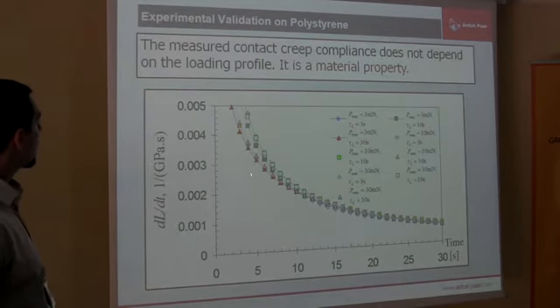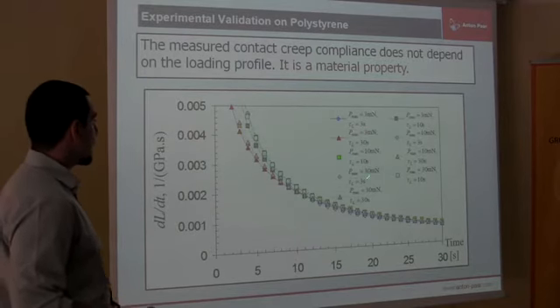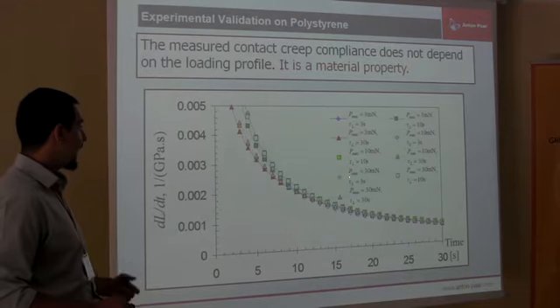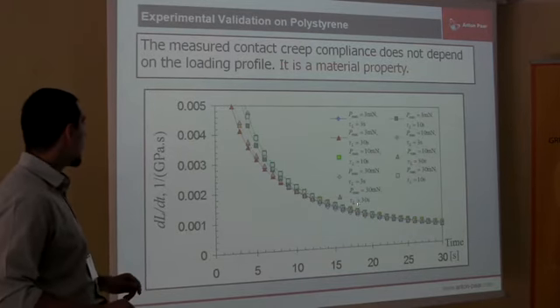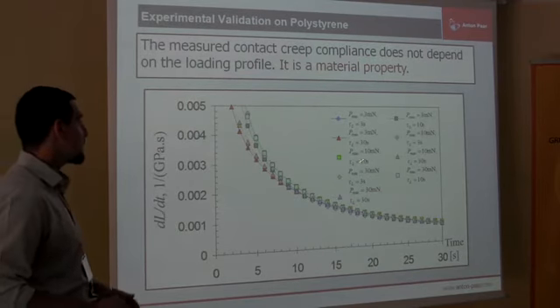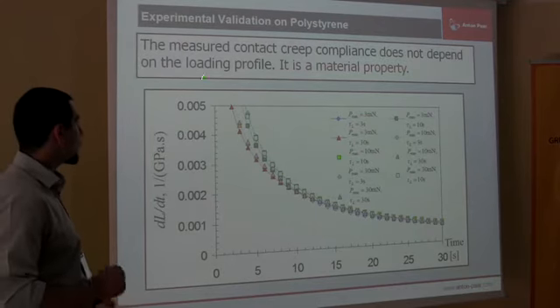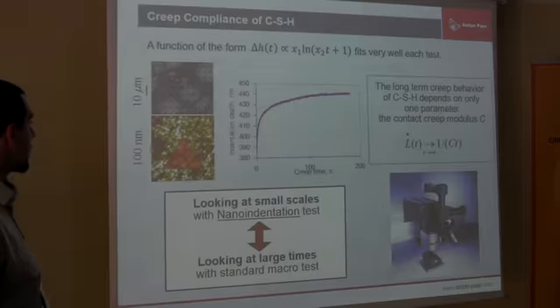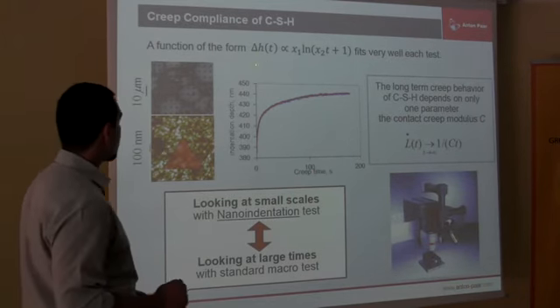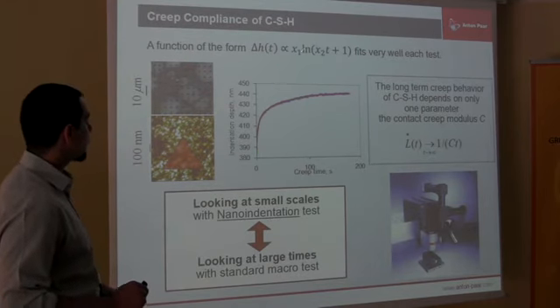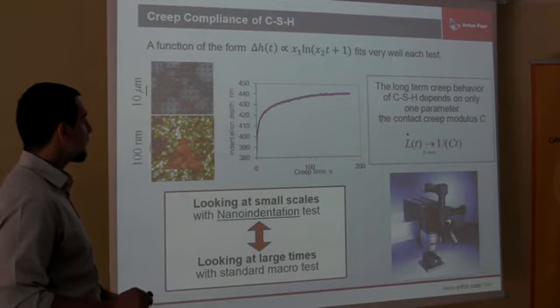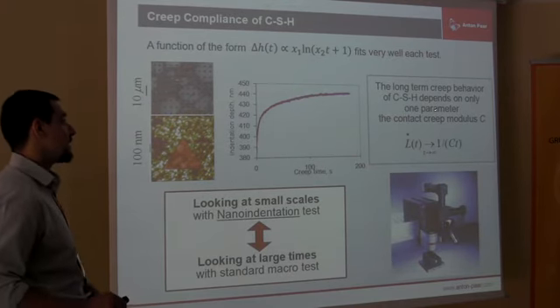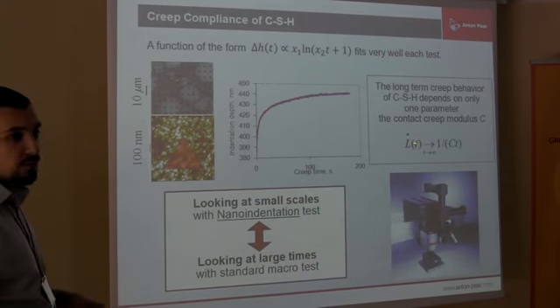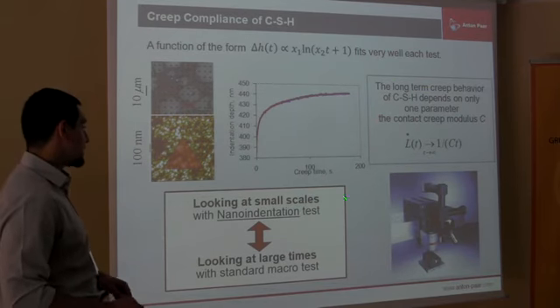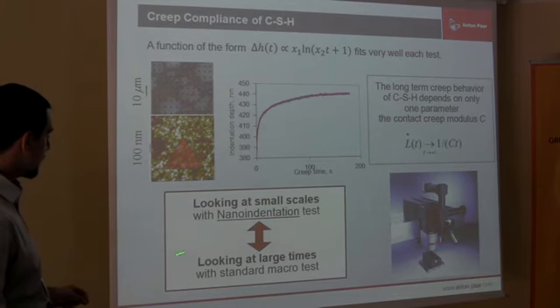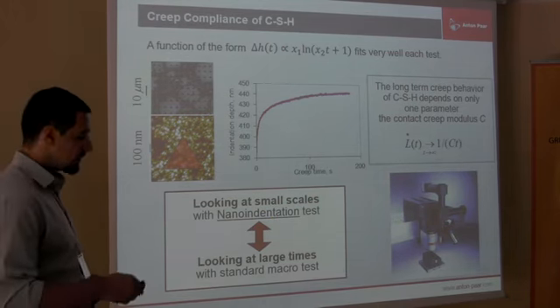We did some experimental validation on polystyrene, and we found that even with different maximum loads and with different times required to arrive at the maximum load, we have the same profile. This means that the creep compliance does not depend on the loading profile, and it's a material property that can be checked. The penetration as a function of time is proportional to the logarithm of the time, which means that the long-term creep behavior of the CSH depends on only one parameter, the contact creep modulus C. This means that looking at small scales with nanoindentation means, in some way, looking at large times with a standard macro test.